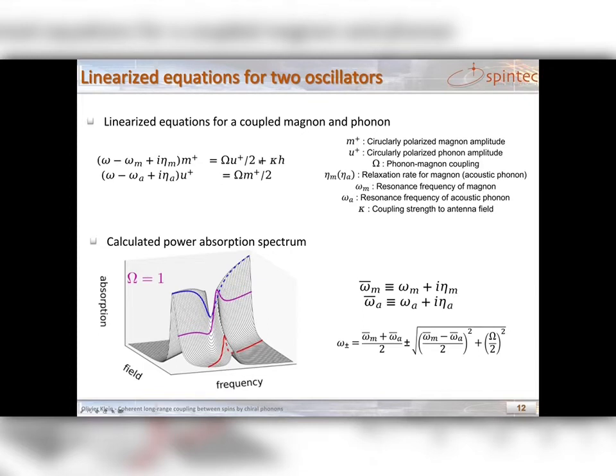So here we want to introduce a simple phenomenological model that can capture some of the observations in previous experiments. We start with two coupled equations of motion, where the magnon amplitude is driven by the magnetoelastic coupling plus the inductive coupling to an external microwave antenna. And circularly polarized phonons are excited due to this magnon-phonon coupling. Analytically, we can solve these two coupled equations of motion to find the hybridized eigenstates. And one can also calculate the absorption spectrum, introducing a relaxation rate for the magnon and acoustic phonon, and this is a 3D representation as a function of field and frequency.